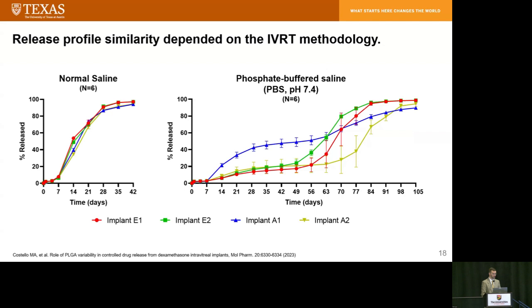Here are the in vitro release data for these 4 batches. And the result here depended on the IVRT methodology that we used. We started with the unbuffered saline release medium. And we saw that the release profiles of all 4 of these batches were not discernibly different. Also, the release lasted about 1 month. And then when we tested these 4 batches in a buffered medium, phosphate buffer at pH 7, the release profiles were different, and then also the release profiles lasted a lot longer.